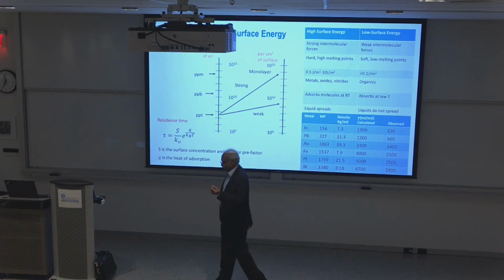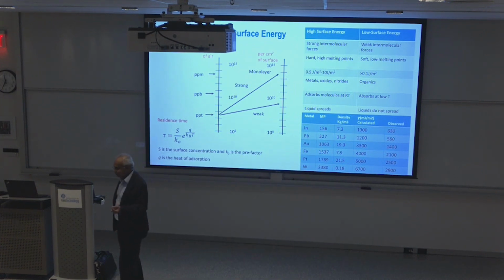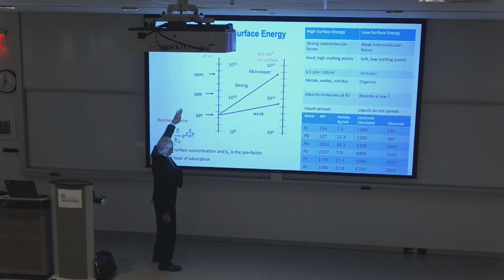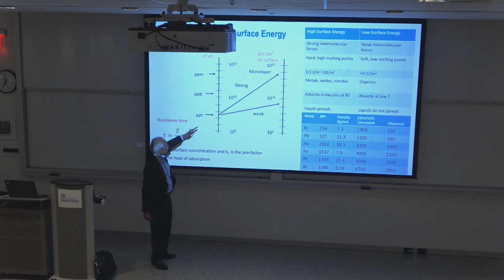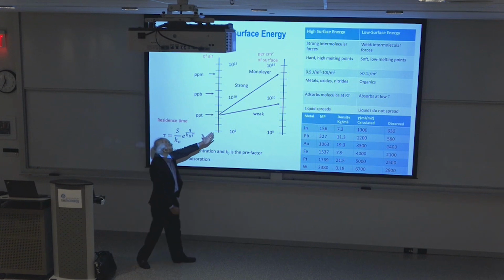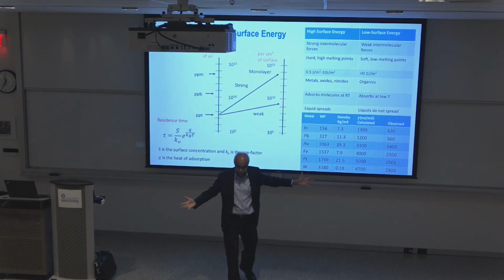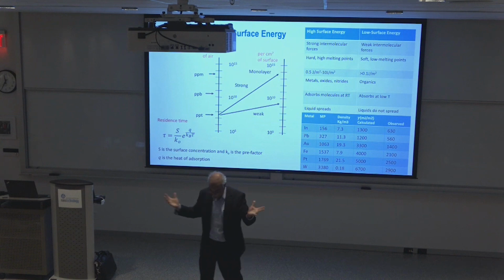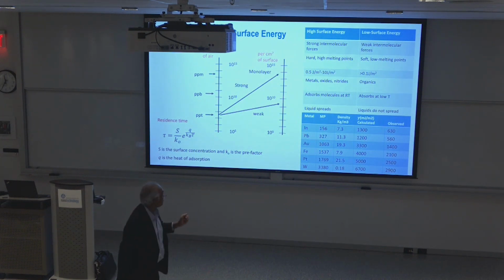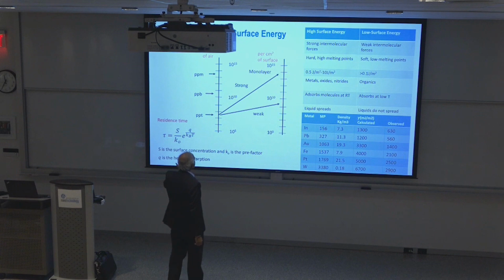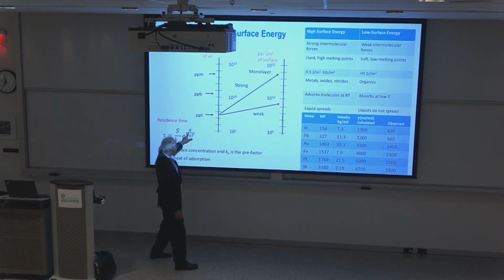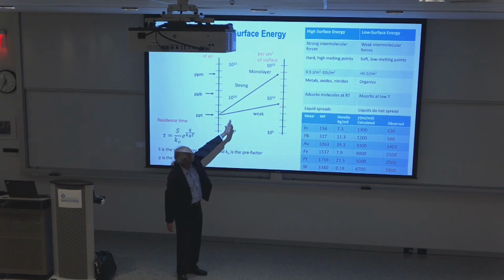So this is the ppt, parts per trillion here, per cubic centimeter. Depending on the interaction between the molecule and the surface, you can get a monolayer on the surface if you have strong absorption. So how do you get strong absorption? Of course, you have the heat of absorption and surface energy. That's what matters. High surface energy materials like metals absorb more; polymers and things like that, with low surface energy, may not absorb that much.